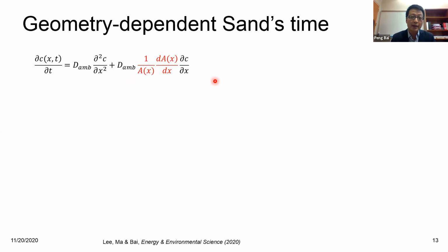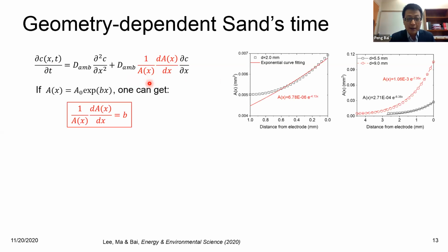But what if we look at this structure? There is some kind of the first order derivative divided by itself. Well, it reminds us, what if we can approximate it by some exponential equation? Then if that's true, this term can reduce to a scalar. And this function becomes a very general, the simplest reaction diffusion equation, which can be solved analytically.